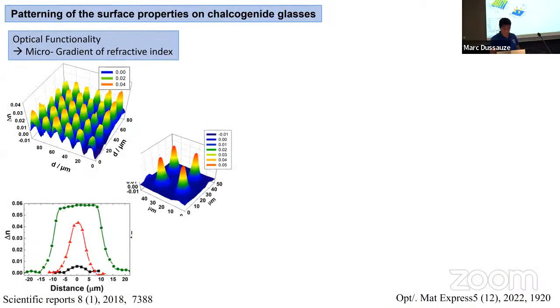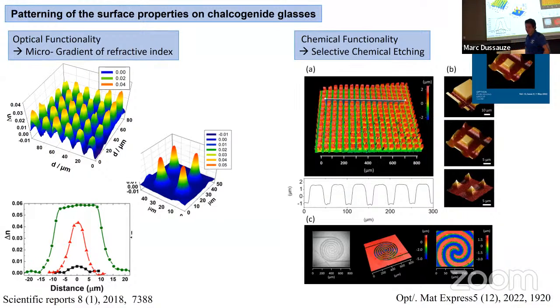All right, so what can we do then with this? If you look at the refractive index, then we can pattern the refractive index and make some microstructured optics like this series of micro lenses that we can obtain. And if you go to the chemical selectivity, selective etching, sorry, then we can get some very accurate patterns of the topology with some depth, which is quite important here, in the order of almost 3 microns of depth. So you can obtain some quite precise patterns like this spiral, for example. So you see here, it's exactly the same process. We are using exactly the same change of structure, change of compositions, and we can tune the optical functionality or the topology of the glass very accurately thanks to this imprinting process.